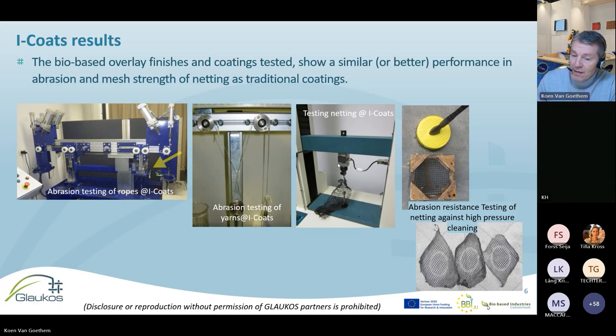positions as well. This one is a tensile tester in which we test the mesh strength and to see if a coating is applied, will it actually protect the knot of a net longer than it would be without a coating. The last one over here at the right is actually to test the abrasion resistance against high pressure cleaning. So it's a device which everybody knows. If you have an outdoor terrace, when you want to clean it after a beautiful winter of humidity like we are experiencing in Belgium for the moment, then you want to clean all the fungi and algae.